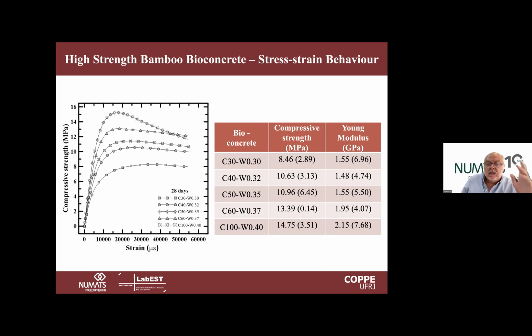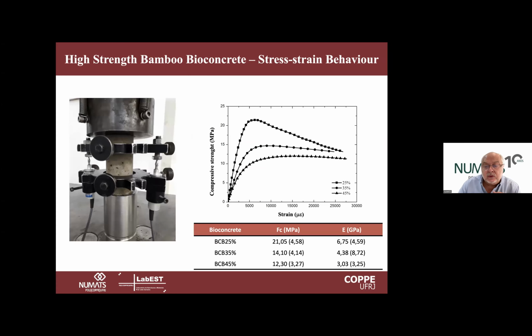But we see here that a good compromise is already obtained when we replace between 40 to 50% of cement by supplementary cementitious materials. In this case, we keep the elastic modulus in the range of 2 gigapascal and compressive strength in the range of 15 MPa, using 40% of biomass. If we reduce the content of biomass to 35 or 25%, we can come up to 20 MPa compressive strength, and we can have elastic modulus in the range of 6 to 7 GPa.